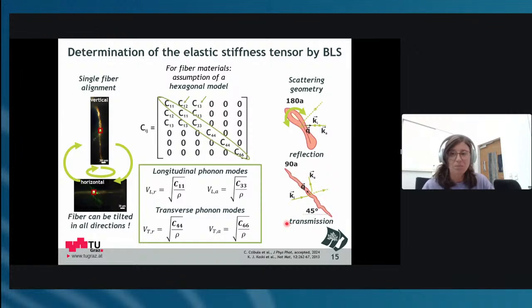The disadvantage about this is you need to get your light through, and the fiber is not perfectly transparent. I would say it's the opposite. These kinds of measurements take a very long time. Usually with 180, for fibers, you can count on about 30 minutes. And here, when you really also do this with the polarizers and then the cross polarizers, you have overnight measurements. So it will go up to 12 hours at least.